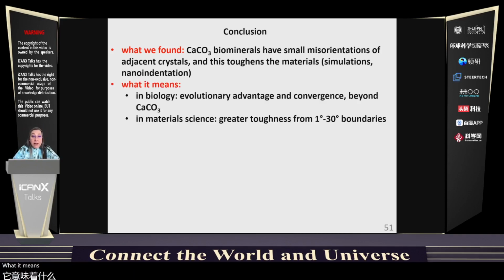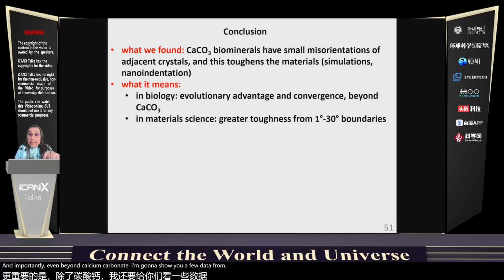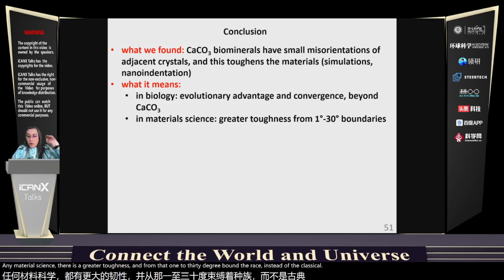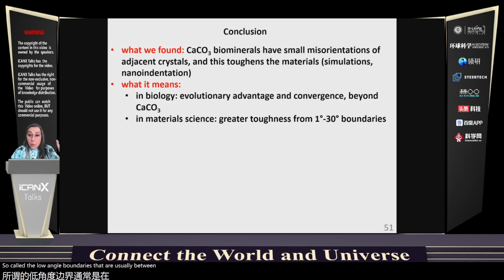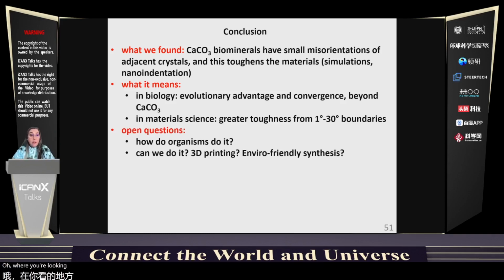What it means in biology is the evolutionary advantage and convergence, and importantly, even beyond calcium carbonate, I'm going to show you a few data from teeth that actually also show this small misorientation of adjacent crystals, and that makes this even more relevant, more general to biomineralization. And in material science, there is a greater toughness from 1 to 30 degree boundaries instead of the classical so-called low angle boundaries that are usually between 1 and 15 degree misorientation. So that's a new way of looking at low angle boundaries.